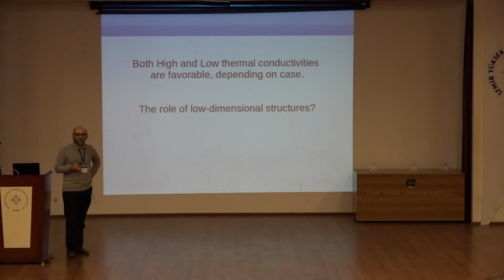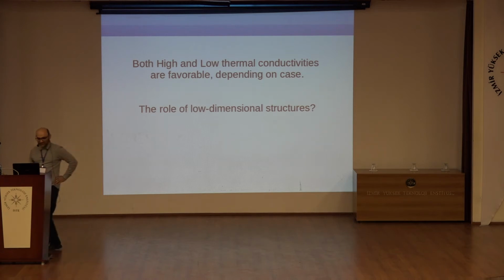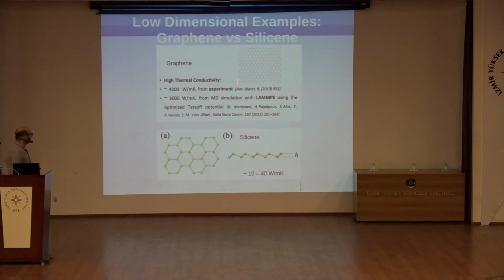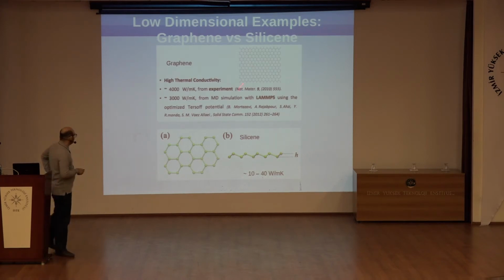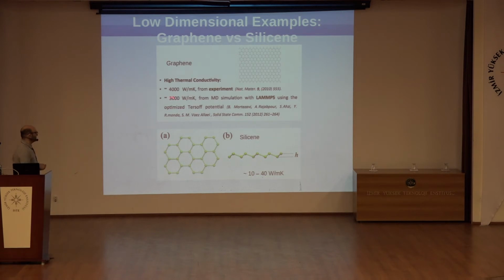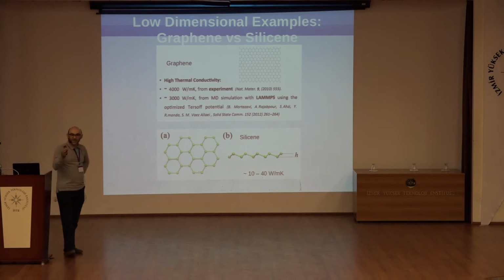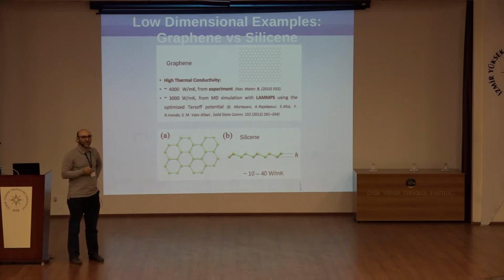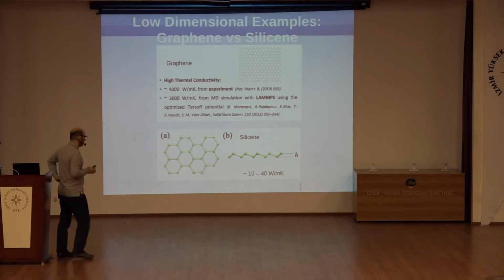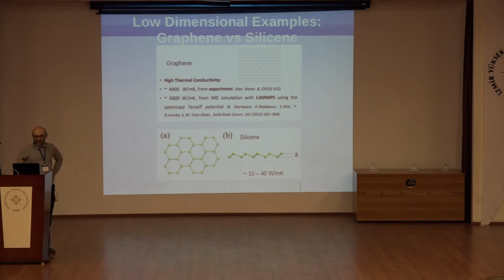But for the case of low-dimensional systems, what we have is both of them. For instance, graphene has very high thermal conductivity. As shown, it is about 4,000 watt per meter Kelvin, but it is not possible to get the same magnitude via molecular dynamics simulation. It is needed to consider a very new approach, which has been described precisely by the previous speakers last day and the day before.